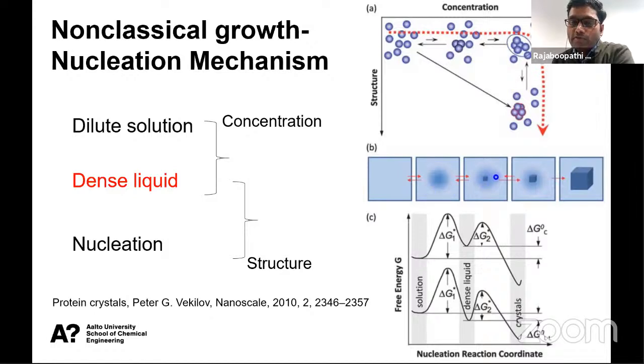So before forming the nucleation cluster, there is a dense liquid state. So we can call it a two-step process, not a one-step process. But in the case of classical, after forming the supersaturated solution, we can get a nucleus. So here, for example, this is the dilute solution. The clusters are attaching together, and again attaching, but the attachment is kind of random here, but it gives some orientation. So from this orientation, you can get some structure. So here, this is the nucleus. If it is classical, after forming the solution, you will reach here. It is a one-step process, but here it is a two-step process.